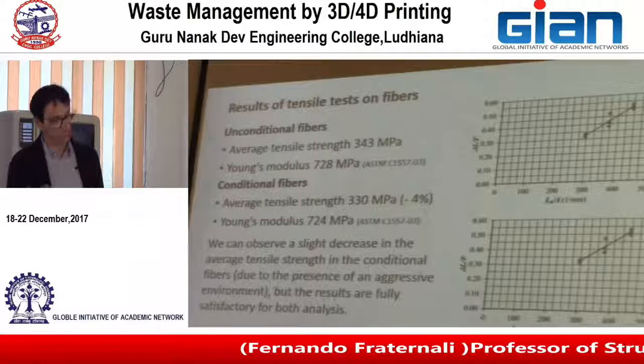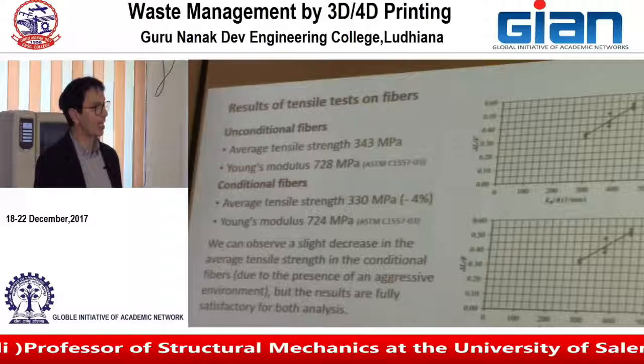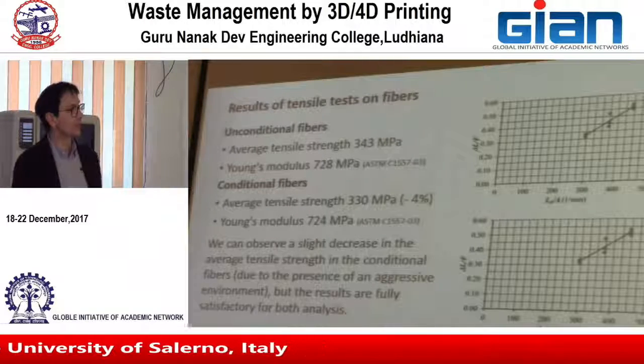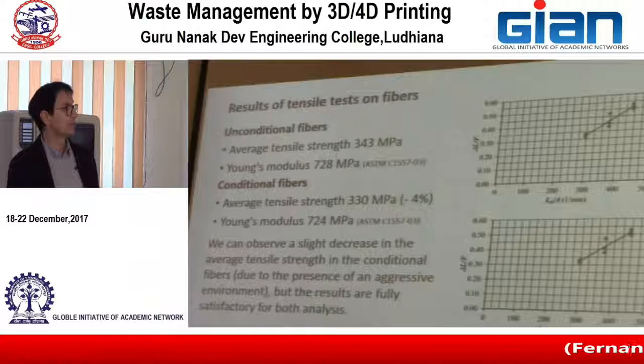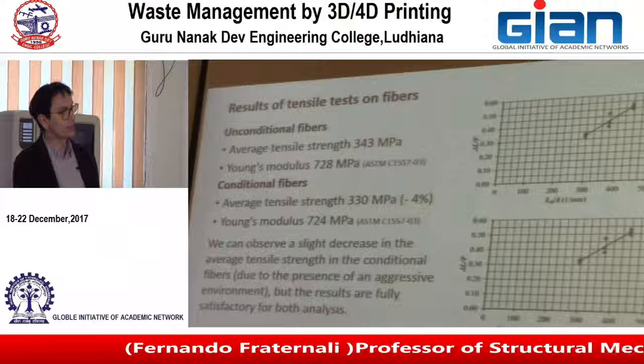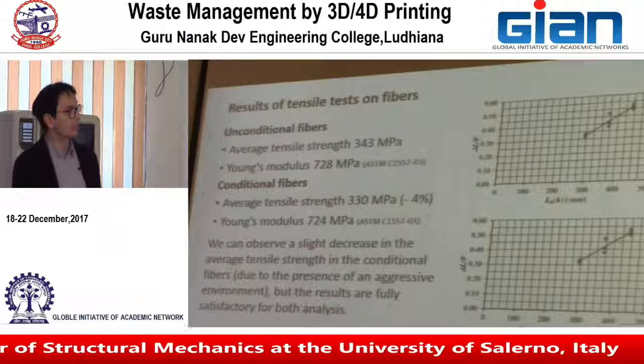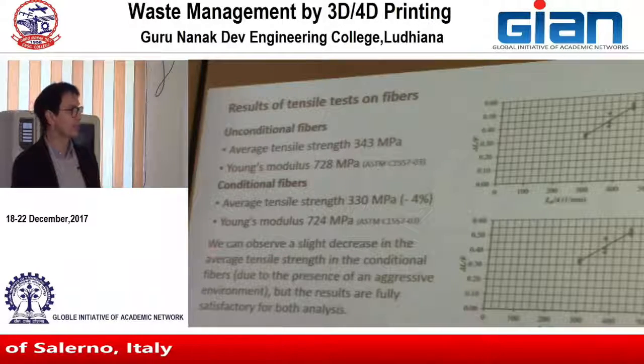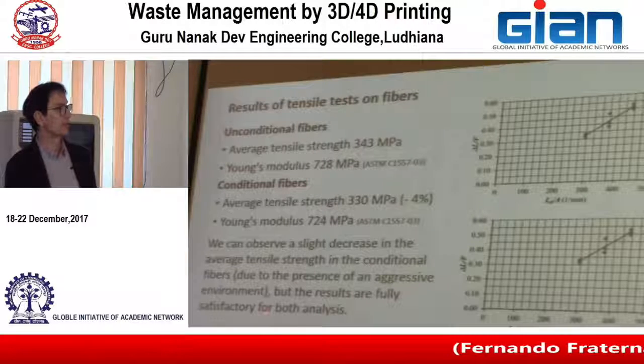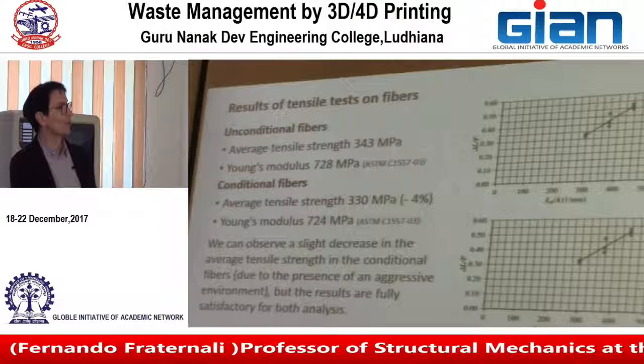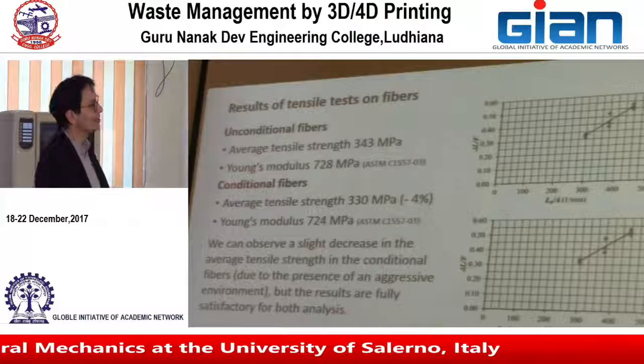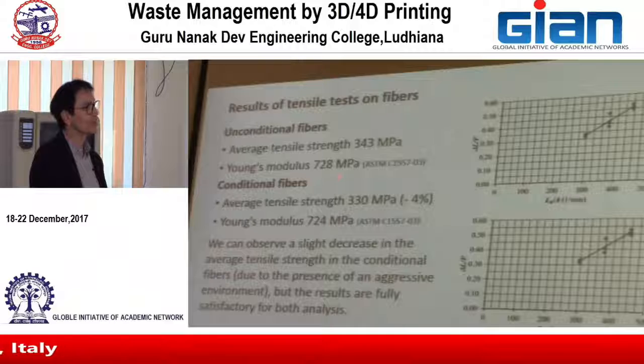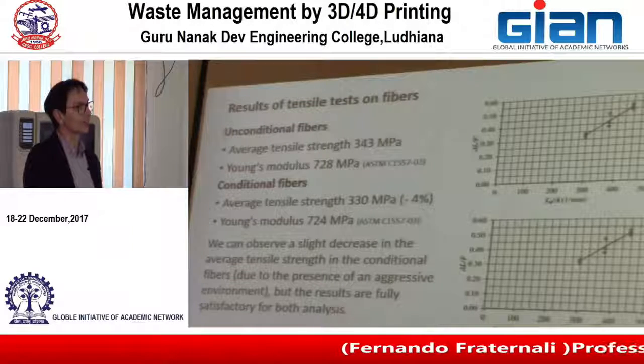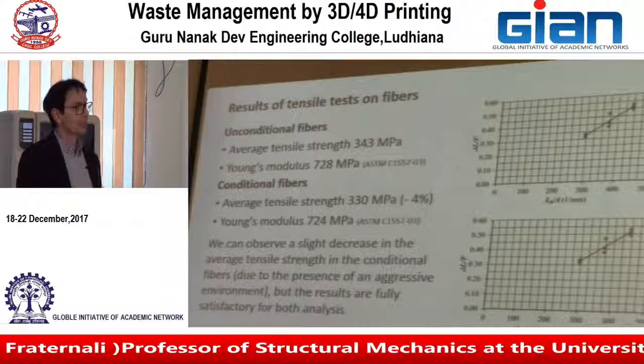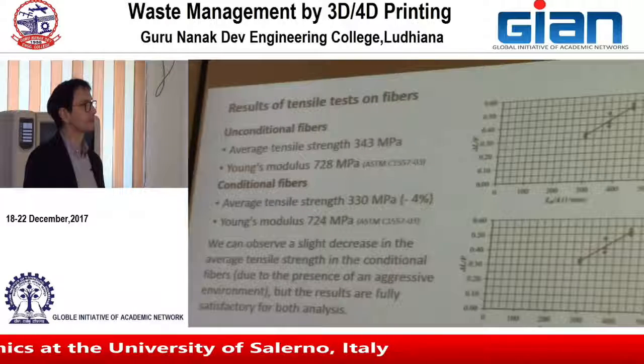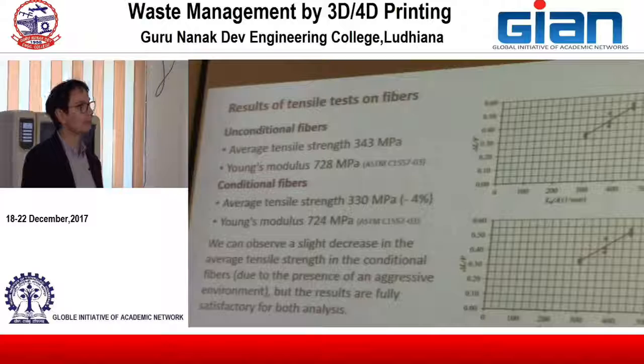And so averaging the results over the three lengths that were considered, comparing also the results for the material without the alkali conditioning and with the alkali conditioning, we observed a slight decrease in the average tensile strength in the alkali conditioned fibers, unconditioned fibers and conditioned fibers. You can see the difference is not dramatic in terms of the Young modulus and the tensile strength. It's minus 4%, which is in line with the results for most plastic materials. And those are the values obtained for the fibers.